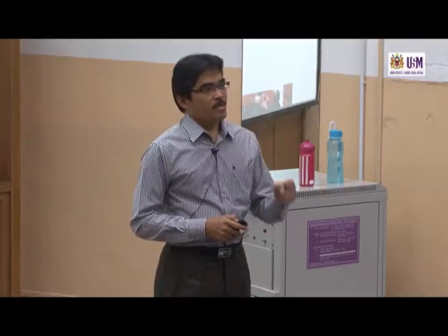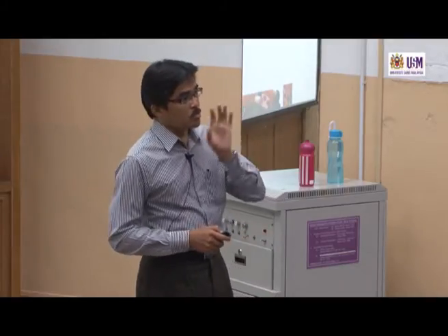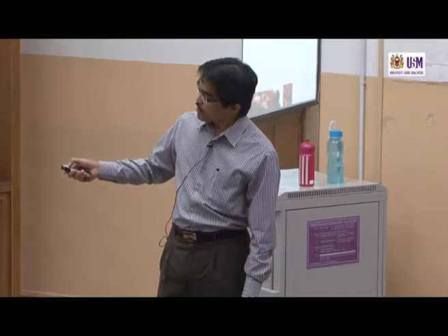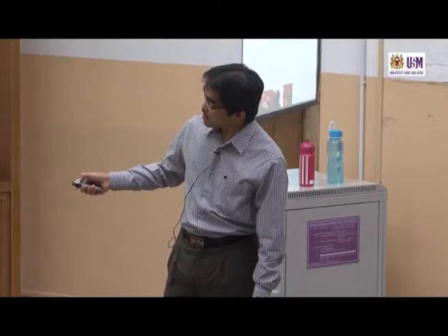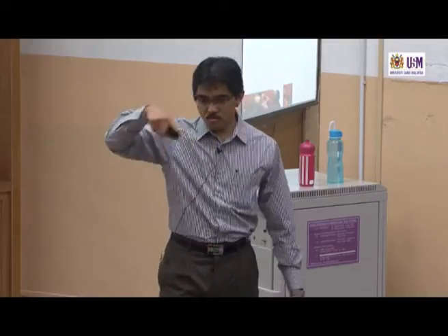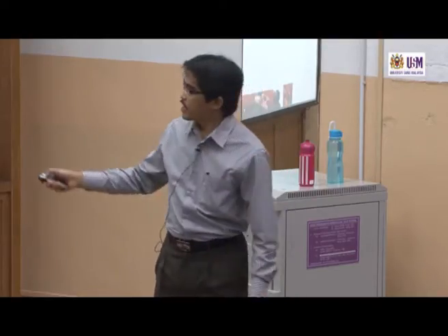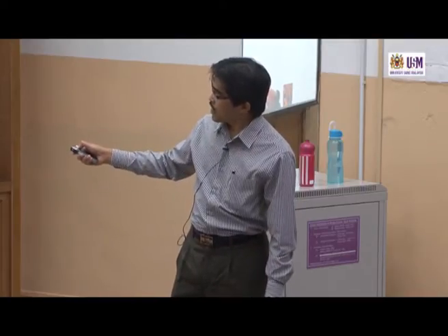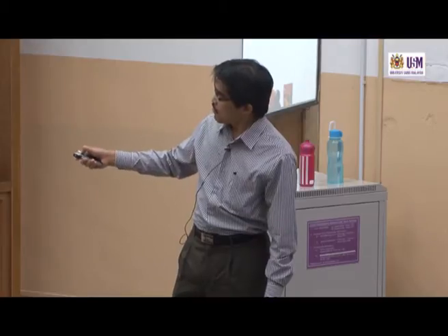Sometimes the surface of the crystal is not smooth. If you look under the microscope, actually the surface of the crystal may not be very smooth. It may have a protrusion like this. So under the influence of stirring, shear, that can cause the small protrusion to break from the main structure and form a new nuclei. And this is called secondary nucleation.